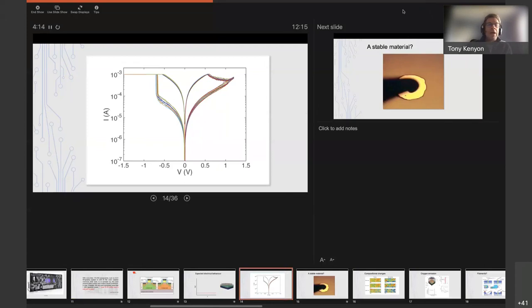Sorry about that distraction. It needs to be a stable oxygen reservoir so the oxygen isn't released to the environment. It also needs to be something that can release oxygen back into the ReRAM cell, into the filament. Yes, sir. So it turns out that one of the ways that we think we can do that quite effectively in our devices is by using titanium. So if we have a silicon oxide layer, and then we put a thin layer of titanium metal, and by thin, a couple of nanometers of titanium metal on top of that, what titanium then does is it's very good at scavenging, taking oxygen out of the silicon oxide.